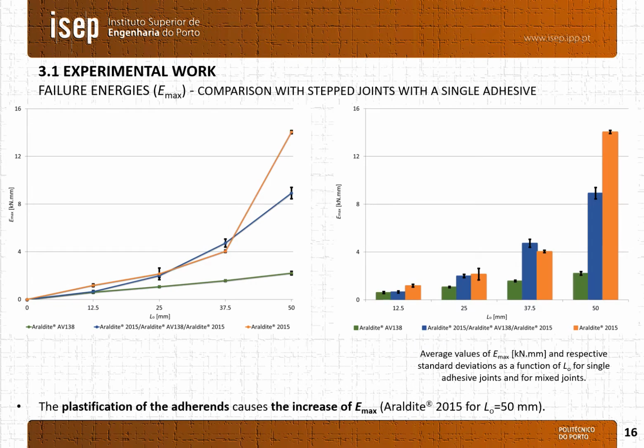When comparing the failure energy between dual and single adhesive configuration, the configuration that presents higher energy is the single adhesive Araldite 2015. The plastification of the adherends causes a remarkable increase of the failure energy, as is the case for an overlap length of 50 mm and with the single adhesive Araldite 2015.